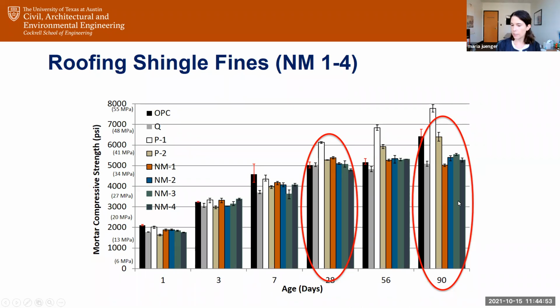However, if you start looking at later strengths, it tells another story and then starts to raise suspicion. If you look at the Portland cement, you have a 28-day strength here of a little over 6,000 PSI, or let's say 42 megapascals. And the pumice is even higher, the pure pumice. The impure pumice is the same as the Portland cement, but you start looking at these others and they never caught up. So it starts to raise suspicion. They're not behaving like the pumices. They're not behaving like a supplementary cementitious material. They're behaving a lot more like the impure quartz. And so the question is, why?